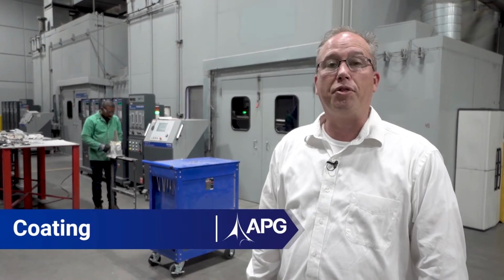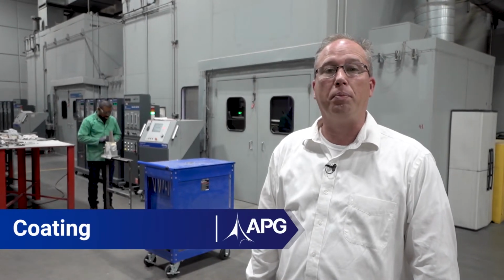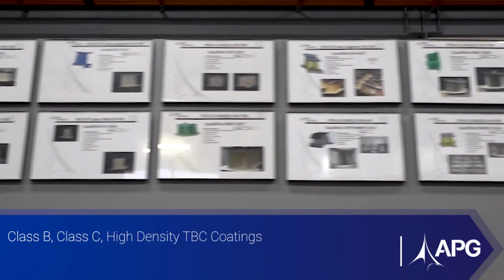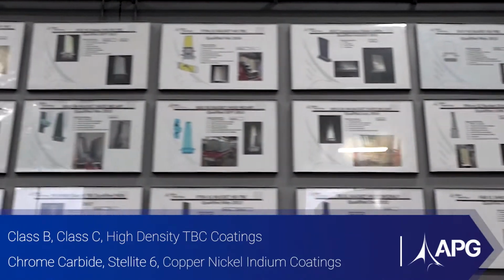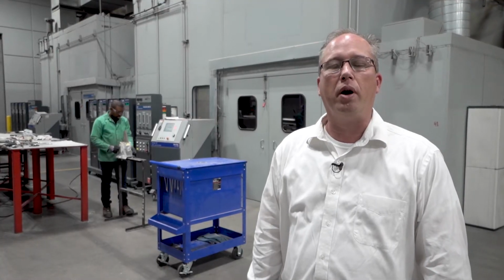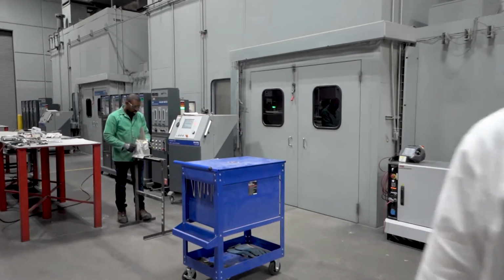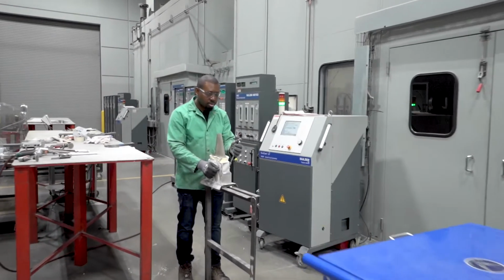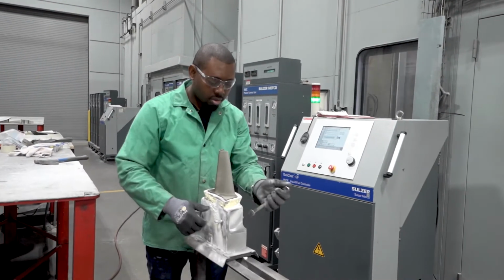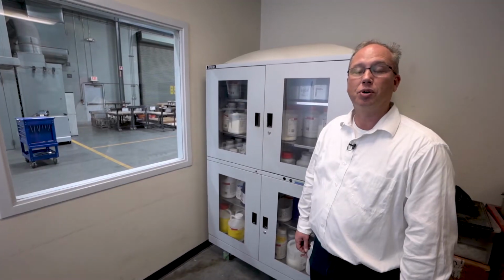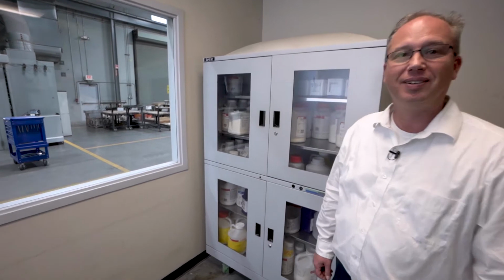In our coating cell, we have 3 coating booths, all HVOF and air plasma capable. We provide Class B, Class C, high density TBC coatings, along with chrome carbide, Stellite 6, and copper nickel indium coatings. All of our coating programs are qualified through our engineering staff. Our coating powder storage is temperature and humidity controlled.